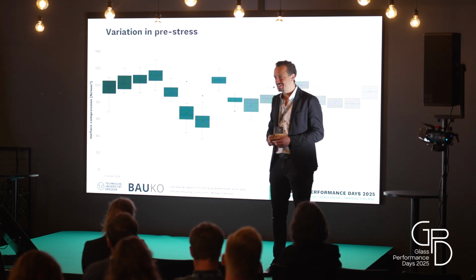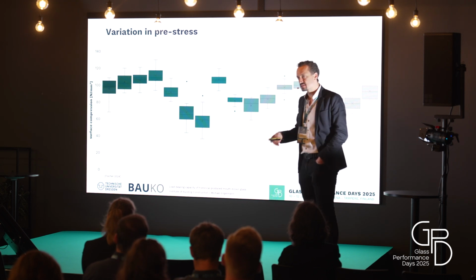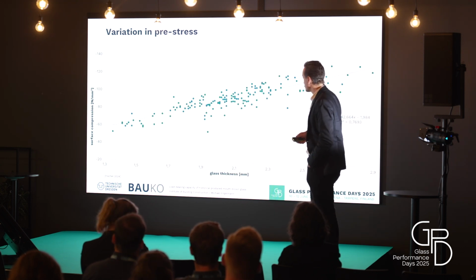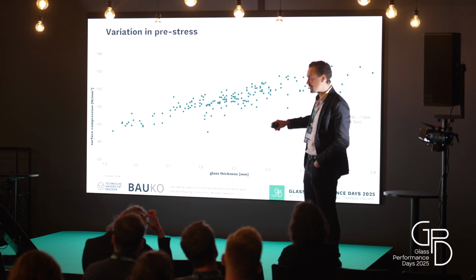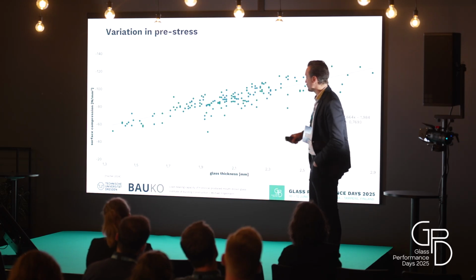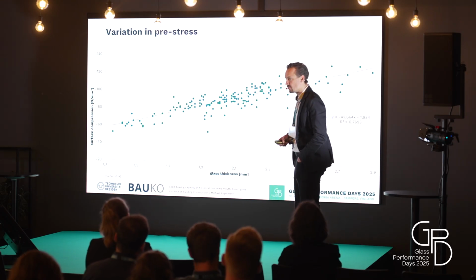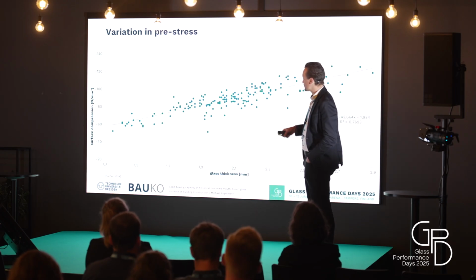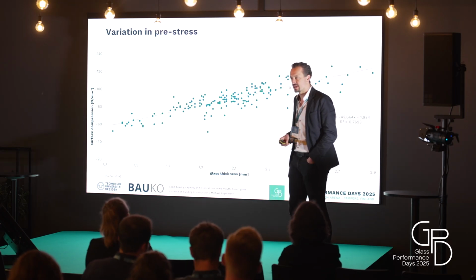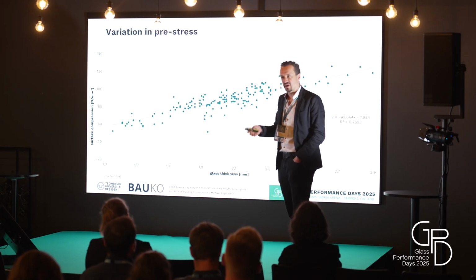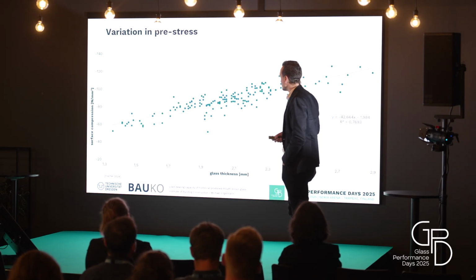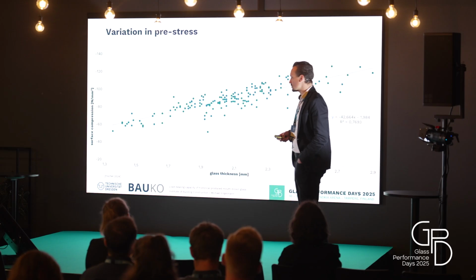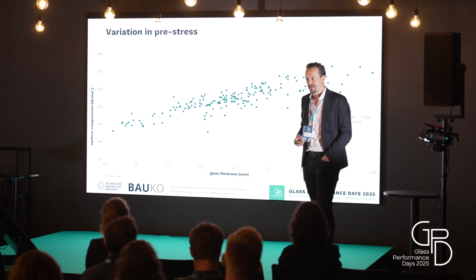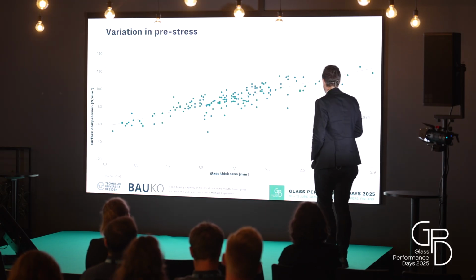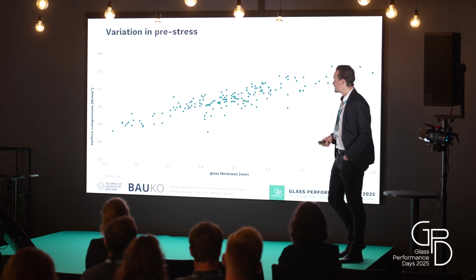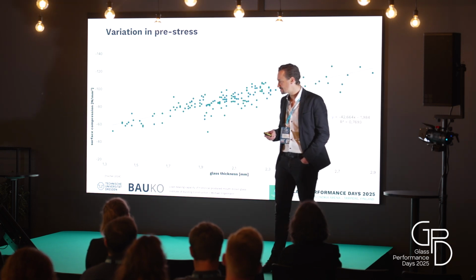The reason for the variation might be the thickness. So we plotted the thickness versus the surface compression. And this is what we found. On the horizontal axis, you find the thickness, from almost 3 millimeters to 1.3 millimeters. This is the average thickness per specimen versus the surface compression. And you see quite a nice linear correlation between those values. So the reason we find quite a spread in surface compression is most certainly caused by the tremendous change in thickness, and the correlation coefficient is quite high, almost 80%. So this model works quite well.